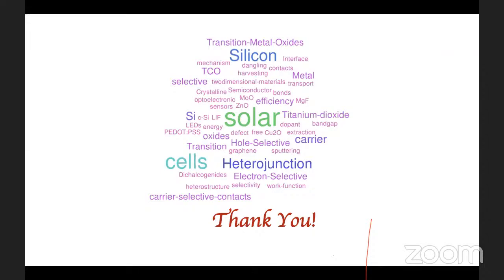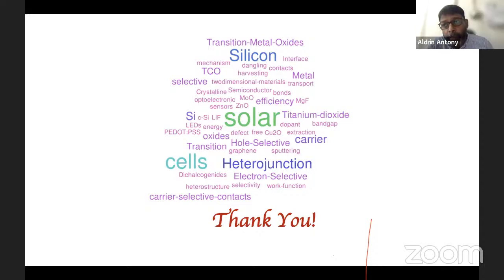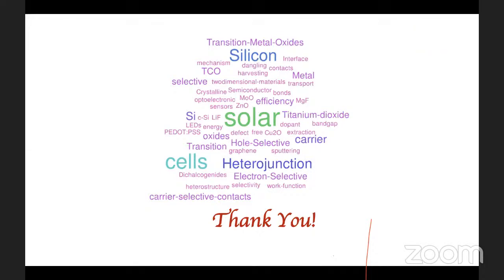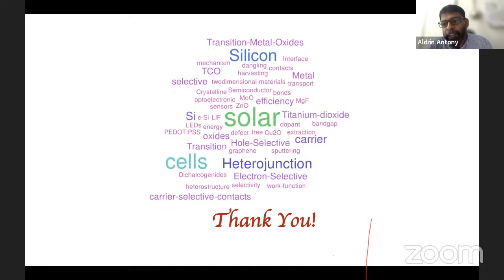Yes, but even with heterojunctions, this has been achieved. It's basically epitaxial heterojunctions that are used for detectors, which show better efficiency as detectors. But when it comes to silicon, it is a very bad detector, for example, if you compare it with other materials. Right. So I'm not sure what exactly you are trying to convey by the line between these two, because in terms of material property, it depends on all the interface defects that come into play for the direct band-to-band transitions, and that is more critical in detectors. Yes. And here you need to find how you could easily extract the carriers, slightly different from recombining band to band. You are selectively removing the carriers from the junction. Okay.